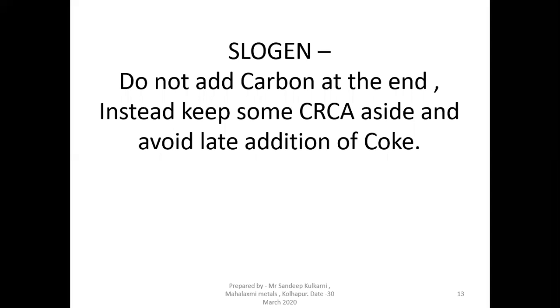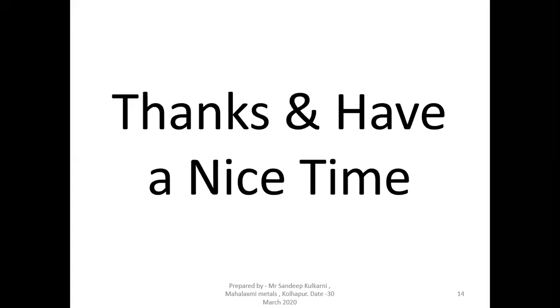One more slogan I would like to remind you, which I have already shared on various occasions: do not add carbon at the end. Instead of adding carbon, keep some CRCA or MS scrap aside so as to avoid late addition of coke or graphite. This is a very important slogan.